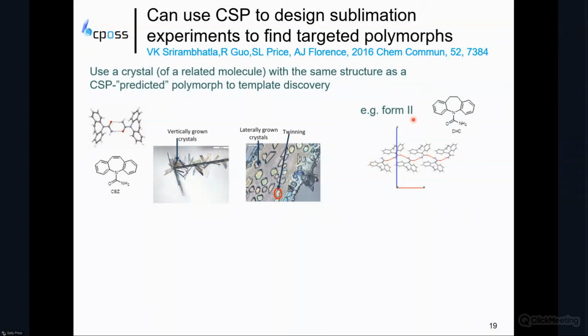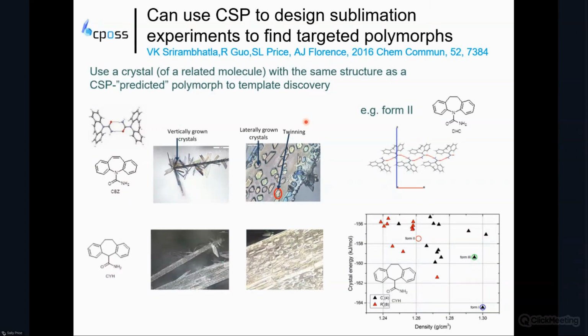So we took form 2 of dihydrocarbamazepine as a template and then sublimed carbamazepine onto it. Now, some of the growth continued on the surface as laterally grown crystals, but there were vertically grown crystals sticking out, which indeed proved to be form 5, a catemeric form of carbamazepine. So we can play this game again using the CSP. With cyheptamide, we found that there was a structure, again isomorphous with dihydrocarbamazepine form 2, between the 2 known polymorphs. We tried the subliming again and got the structure we had predicted. Brilliant.